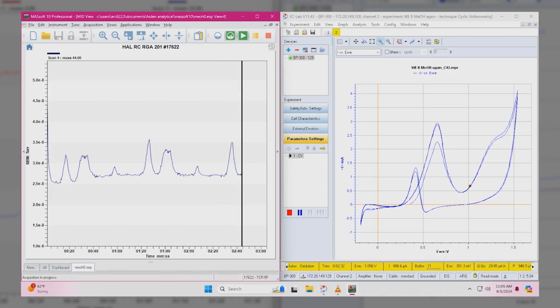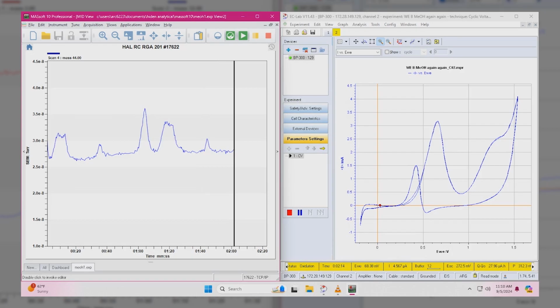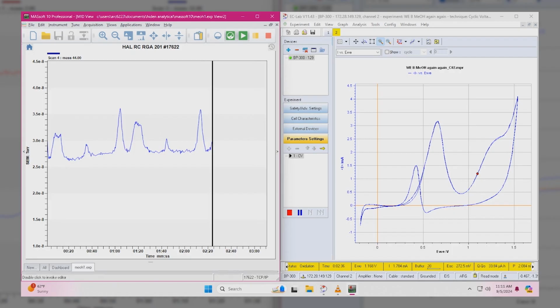So now we're going to do CVs in 0.5 molar sulfuric acid with added 0.5 molar methanol to the solution. And we're going to monitor the 44 response, which is representative of the production of CO2. And you can see as the potential is scanned, there are 3 regions of this CV where CO2 is actually being produced. And we can monitor that in real time with the mass spectrometer. Methanol oxidation is known to have other products at these potentials, but we are monitoring 44 because that is the dominant product of methanol oxidation over a platinum surface.